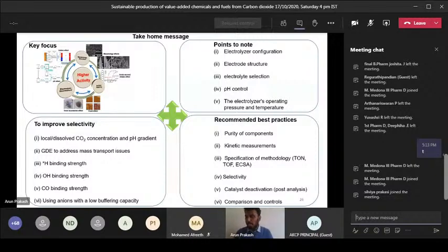Kinetic measurements are very important for understanding the electron transfer kinetics, and specification of methodology is very important. There are different methodologies available in literature. You have to find the best one, and you have to use that methodology for calculating the turnover number, turnover frequency, electrochemical surface area. These are the key descriptors of CO2 reduction activity. So you have to care about which best method you are going to use for your calculation. And selectivity, catalyst deactivation, and comparison and control.